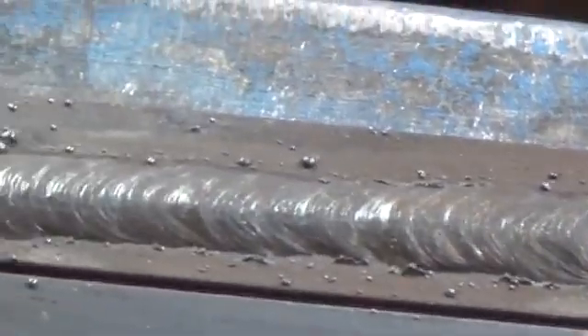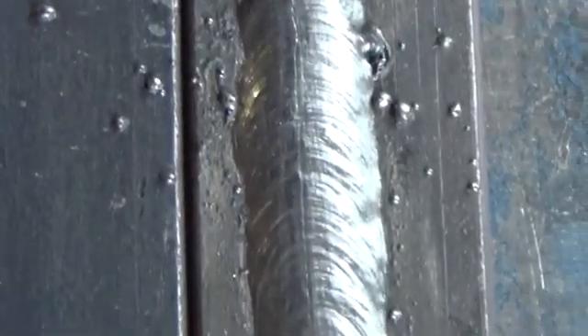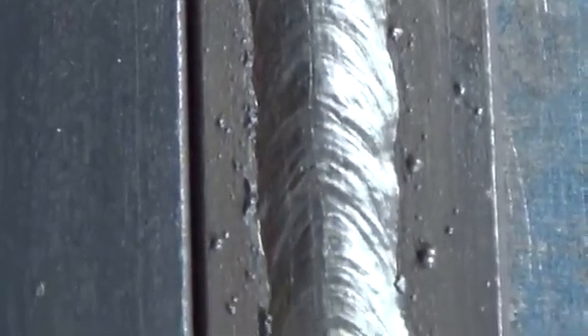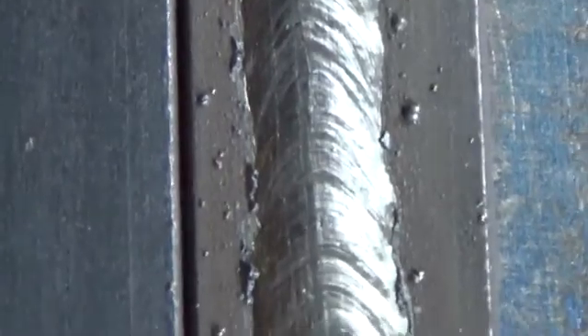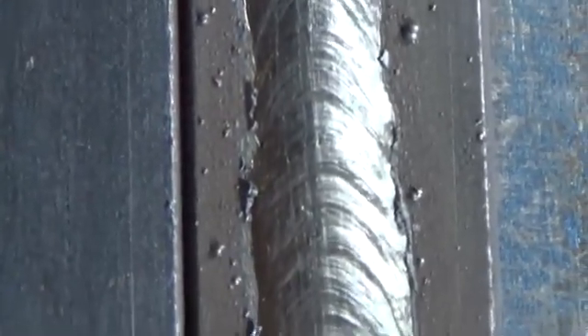And finally the third weld: rutile coated electrode negative, current is 95 amperes. Look at the fact that the puddle is very fluid. It's difficult to manage. Metal excessively spreads over the surface. Quite a lot of large and small spatters are produced around the weld. Welding at this current is very fast. The arc is very bright. Clean off the slag and inspect the weld. The width of the weld is more than necessary. Excessively flat top. We see a large amount of spatters, which is not typical for rutile electrodes.